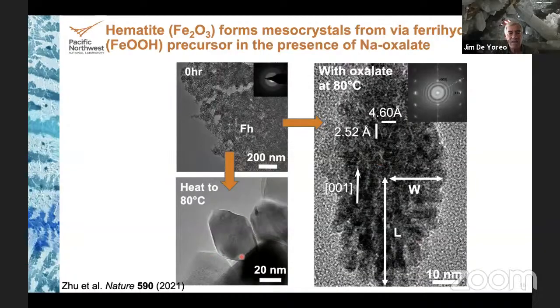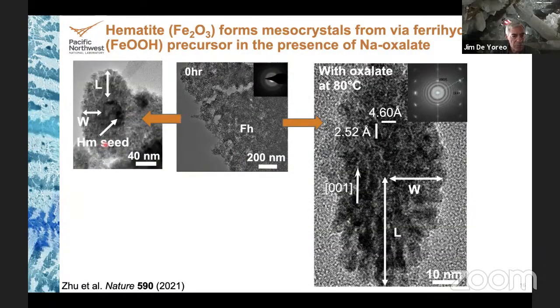If you take preformed, beautiful hematite crystals, throw them back in with ferrihydrite and put sodium oxalate in, you get a similar result, which is a spindle. But now the particles have added on around the seed, and the 001 axis of the seed now defines the 001 axis of the spindle. And interestingly, if you measure the length to the width of added material, it has the same aspect ratio as the aspect ratio of the spindles formed without the seeds.